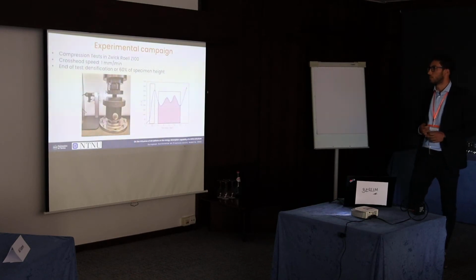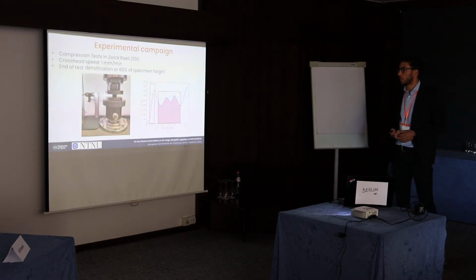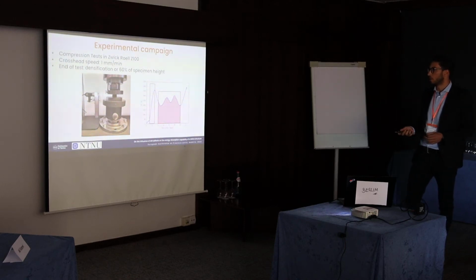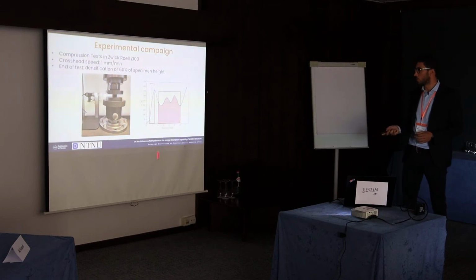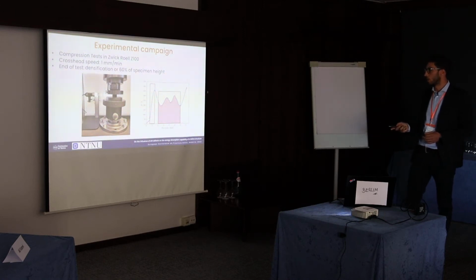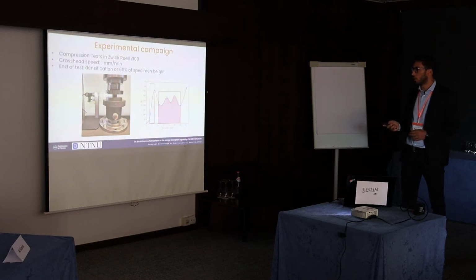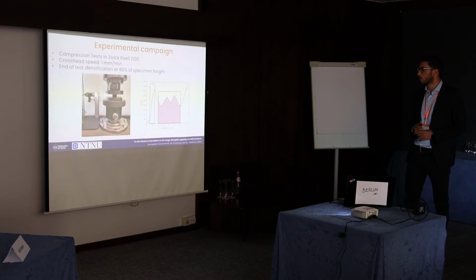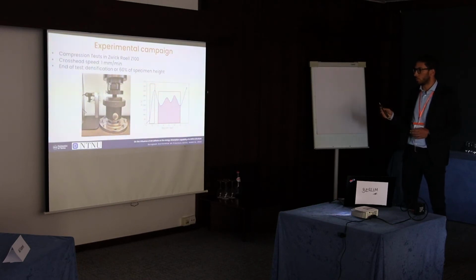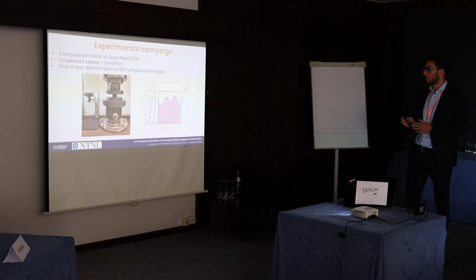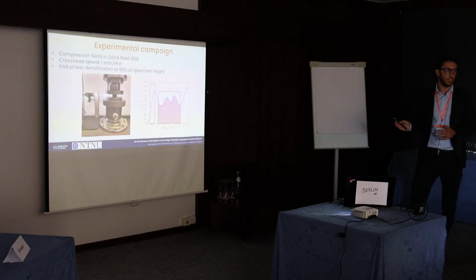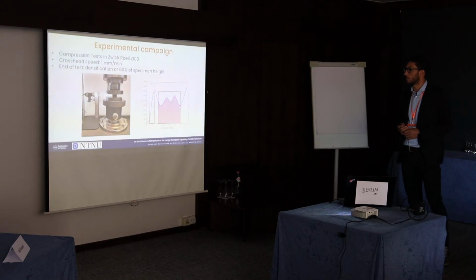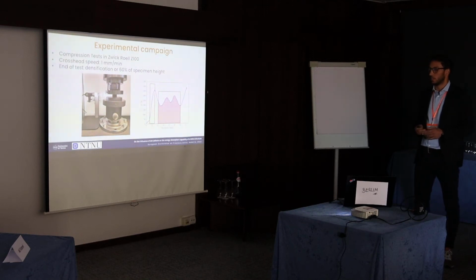These are some of the specimens that we produced. So after the production of the specimens, we conducted the compressive test in a static manner. And there you can see also how we calculated the energy absorption from the force displacement curve. In particular, right after the peak force, we integrated the force displacement curve in order to obtain the energy. And this integration was performed until the densification occurred in the test. Indeed, the tests were ended when densification occurred or when 60% of the specimen height was reached.